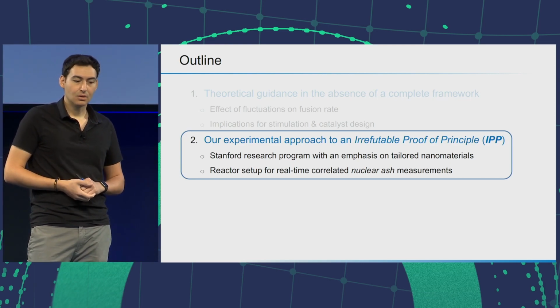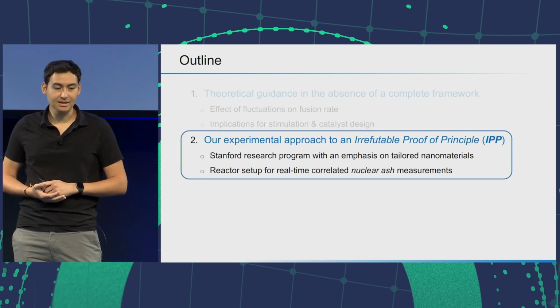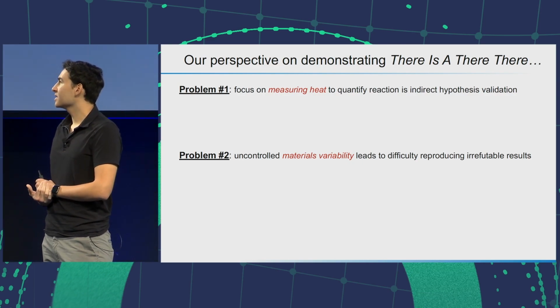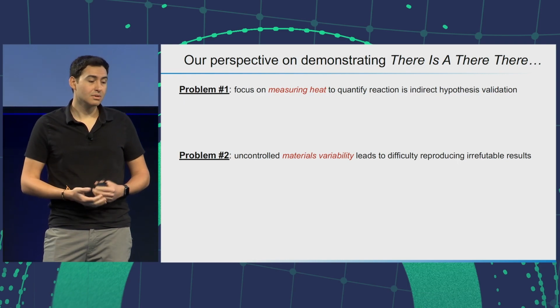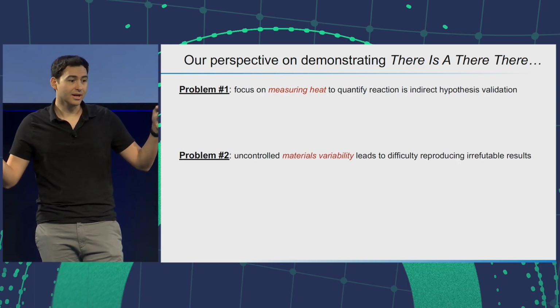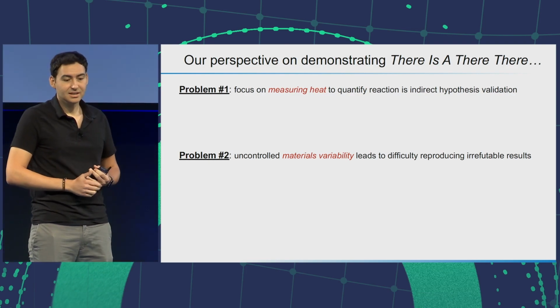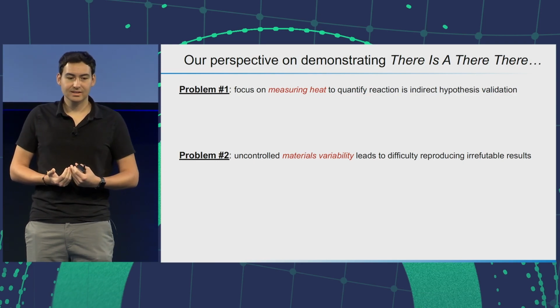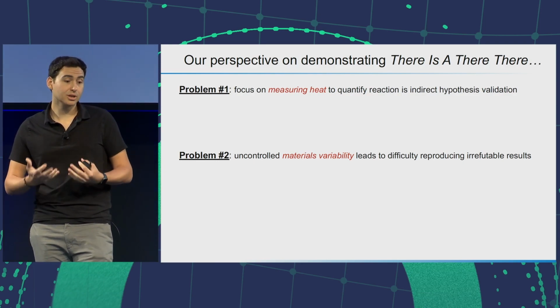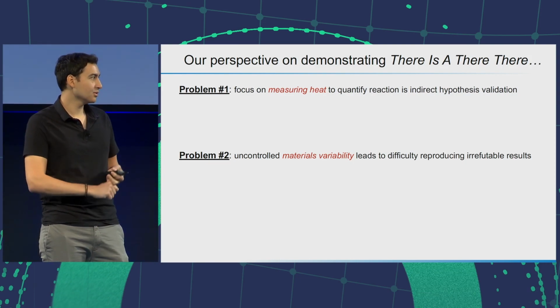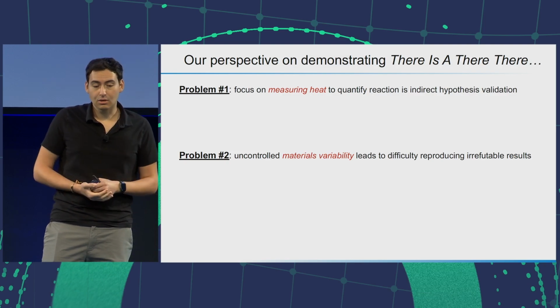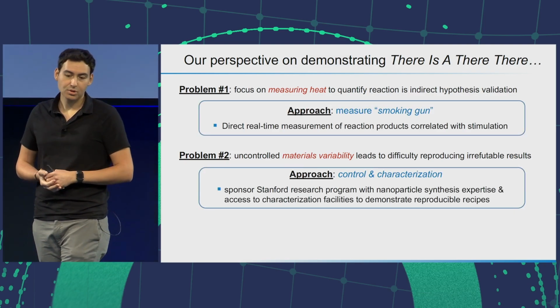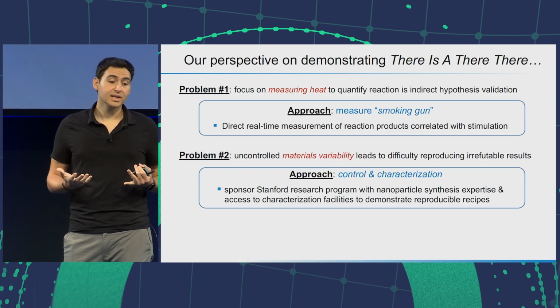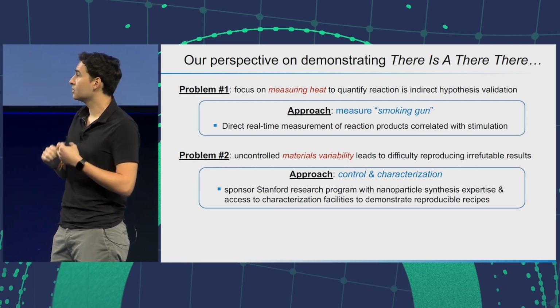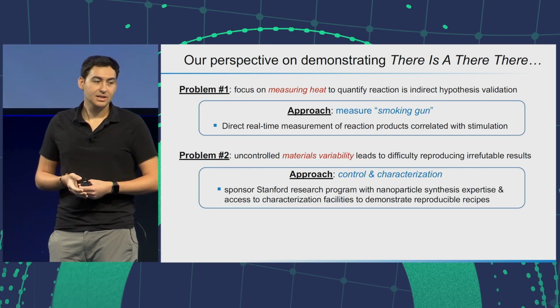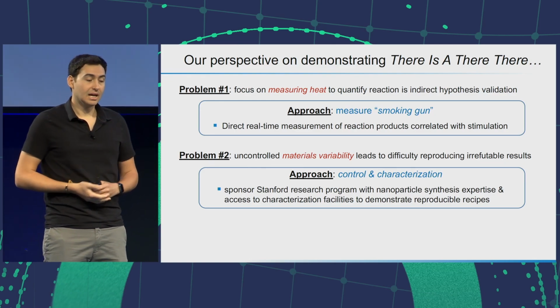Now I want to tell you a little bit about where we are in setting up the experiment for what we call, again, the IPP, an irrefutable proof of principle experiment. And so in assessing the field, we had our own perspective on what we thought were the problems that we would like to address in showing that there is a there. The first one was the focus on measuring heat. It was our opinion that that's indirect for hypothesis validation. What we really want to do is see nuclear ash. And number two, the uncontrolled materials variability was a big issue that we wanted to address in our approach. The two solutions that we used to guide our program were, number one, target the smoking gun, look for helium in our case. And number two, introduce a strong level of control and characterizing our nanomaterials so we're confident what we're putting in our reactor each time is the same and reproducible in that sense.